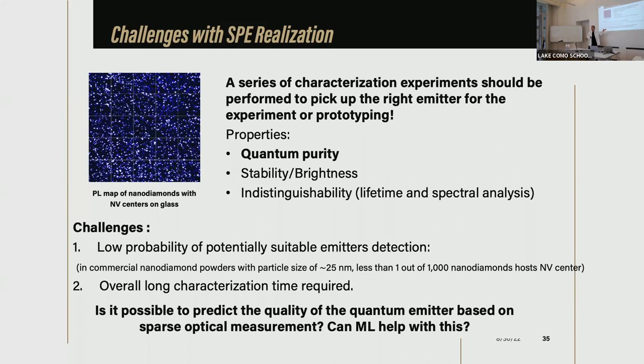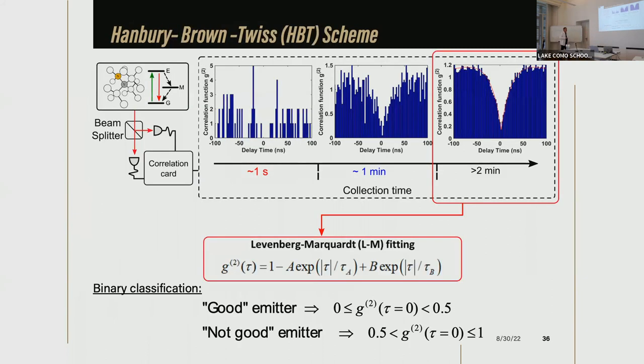The question is, could machine learning help to do it much faster, if you would like to do this quantum photonic circuitry? This slide illustrates what we normally do. To measure this autocorrelation function, you have this correlation setup with 2 arms, and you measure this signal photon coincidence event as a function of delay. After several minutes, you have a spectrum like this, then you use this Levenberg-Marquardt fitting, take the delay equals 0 between 2 pulses, and if it's below 0.5, we say this is a single photon source.